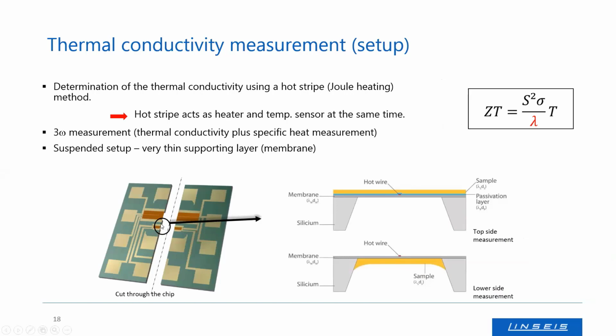If we cut the chip and have a look on this side of this membrane, we see what is depicted here. So there are rims made from silicon. On top is a very tiny membrane of 100 nanometer thickness. There is a hot wire implemented. A passivation layer is coating this membrane and the hot wire. And on top, the sample was deposited.